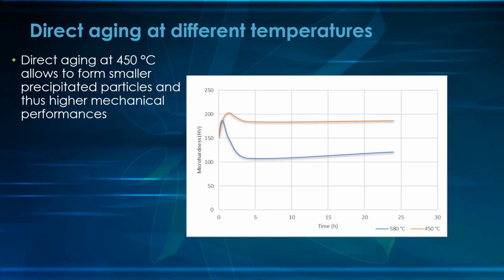The following step of the research was to perform direct aging of the alloys. So aging performed directly on the as-built specimen at two different temperatures, 580 degrees centigrade and 450 degrees centigrade. The results are reported in the slide, so you can see that by lowering the aging treatment temperature, the microhardness peak will be reached after a longer time because the diffusivity is lower, but it is possible to reach very high hardness values.